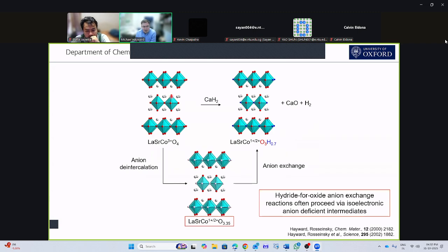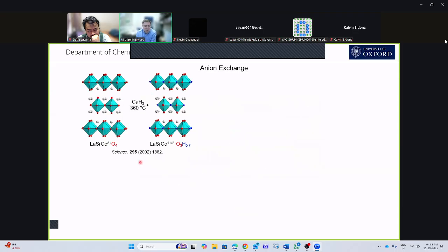Now this reaction actually goes through an intermediate. You can think of this reaction as first doing the anion extraction that we were just talking about to make this phase LaSrCoO3.35. Then there's a second step in which we replace 0.35 oxide ions and 0.35 vacancies for 0.7 hydride ions in a redox neutral anion exchange reaction. What we'll see in the remainder of the talk is that sometimes we see this intermediate and sometimes we don't. But this hydride for oxide anion exchange is rather interesting and allows us to make rather exotic compounds. So we can make oxyhydrides of the transition metal oxides that we start with.